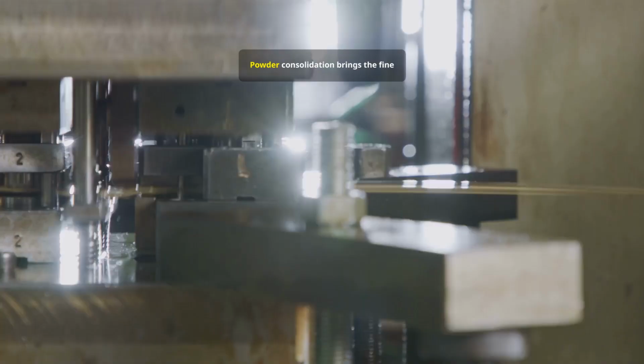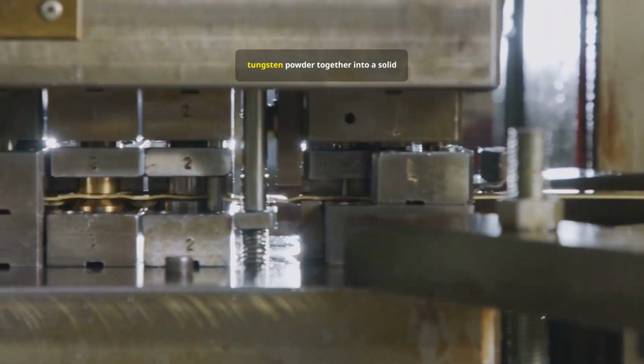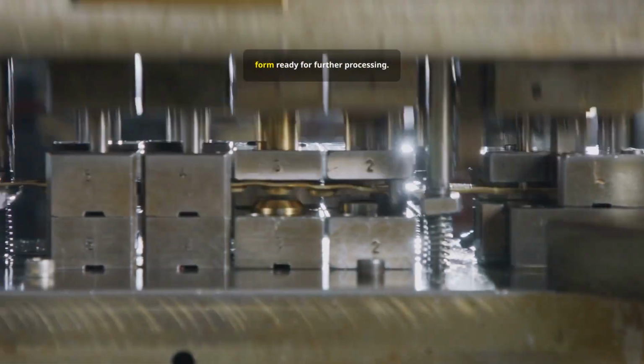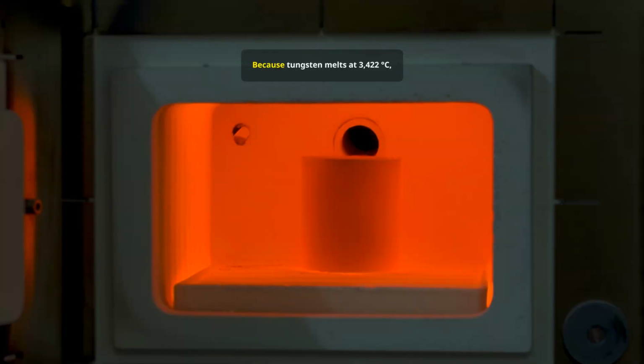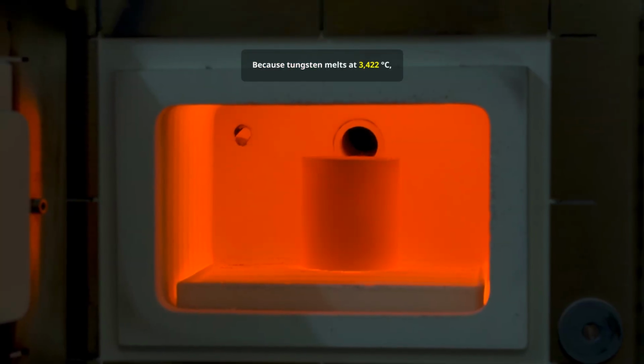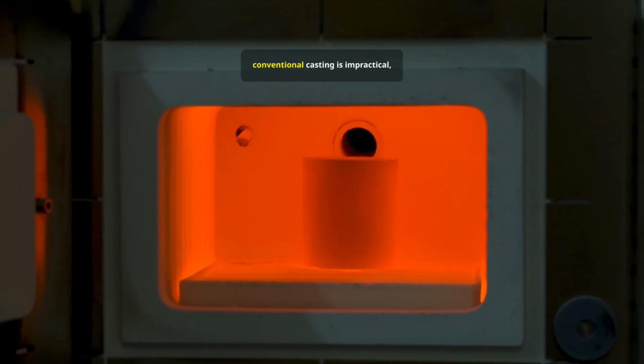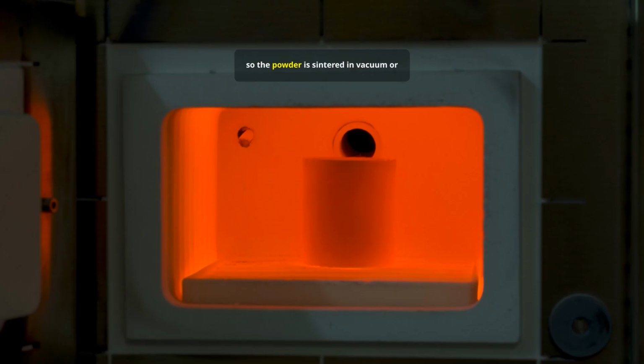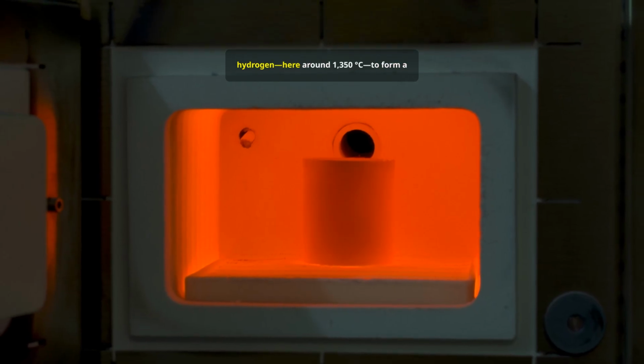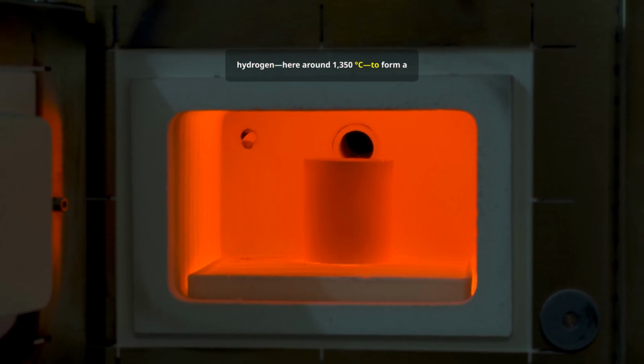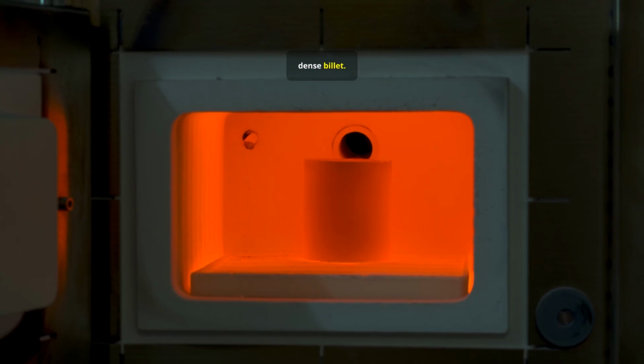and gas flow. Powder consolidation brings the fine tungsten powder together into a solid form, ready for further processing. Because tungsten melts at 3,422 degrees Celsius, conventional casting is impractical, so the powder is sintered in vacuum or hydrogen, here around 1350 degrees Celsius, to form a dense billet.